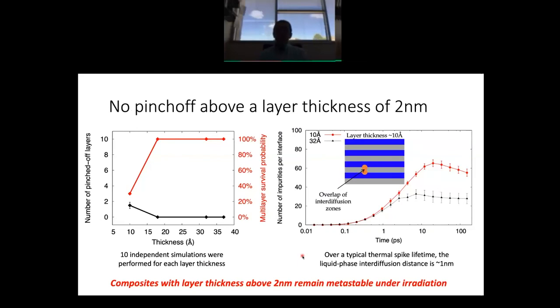We repeated these simulations for multi-layers of a variety of thickness. So we investigated layer thicknesses of 10 angstroms, layer thicknesses just below 20 angstroms, just above 30 angstroms, and just above 35 angstroms. And for each of them, we did these phase field simulations, and then we counted the number of pinched off layers as a function of layer thickness. And what you can see here is that we see these pinch-offs occurring at the low layer thicknesses, but when the layer thicknesses become higher, we no longer see the pinch-offs, okay? You can also plot this as a kind of survival probability, right? Multilayer survives if there are no pinch-offs. It does not survive if there is a pinch-off. So the survival probability at low layer thicknesses is low. Then as soon as you get to about 20 nanometers layer thicknesses, the survival probability goes up to 100%.